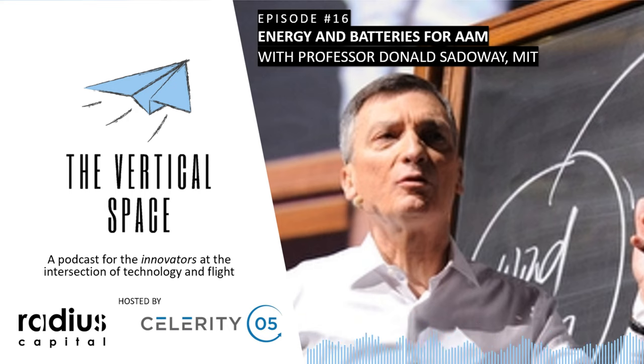Well, I think lithium metal is a step in the right direction, giving you much more, to your earlier point about increasing the active fraction. Right now, in the negative electrode, you've got this graphite host, which is just sitting there. It's basically a parking garage for lithium. If you get rid of that garage and just have the lithium as lithium metal, you get a gigantic increase in energy. Pure lithium is over 3,800 milliamp hours per gram, whereas with graphite filled up with lithium, you're down below 400 milliamp hours per gram. So that's a step in the right direction.